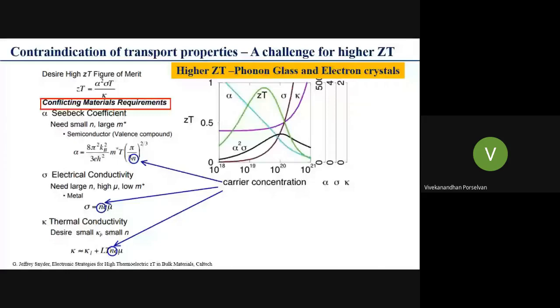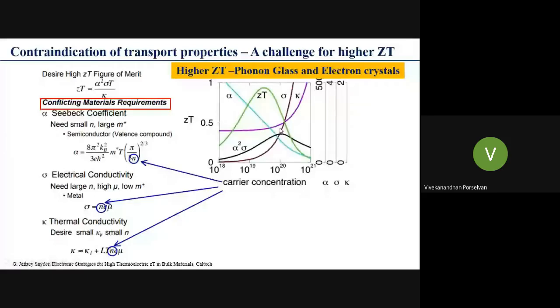If you look at it, a higher carrier concentration leads towards a higher thermal conductivity. The violet color shows the thermal conductivity, and as the carrier concentration keeps increasing, there is a chance of higher thermal conductivity, which is undesirable. If you look at the Seebeck coefficient, the higher the carrier concentration, the lower the Seebeck coefficient, S value. Whereas talking about the electrical conductivity, a higher carrier concentration will significantly increase the electrical conductivity.